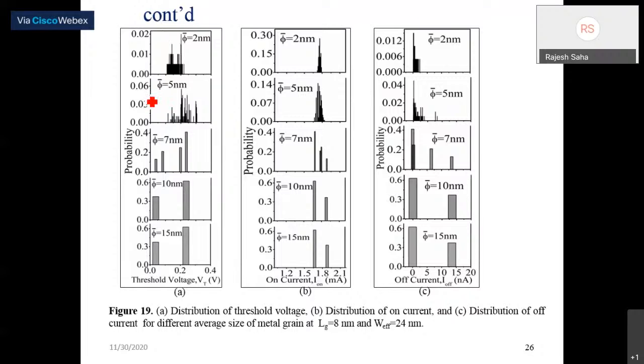And for better visualization and better explaining of the results, we have plotted the distribution of the threshold voltage, on current, and the off current. As you can see, for small grain size, it is close to normal. For larger grain sizes, like 10 nanometer and 15 nanometer, it is a bimodal distribution. As you go from grain size 2 to 10 or 15 nanometer, the variation in the threshold voltage increases.